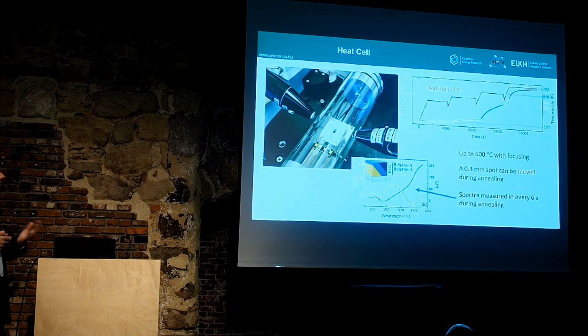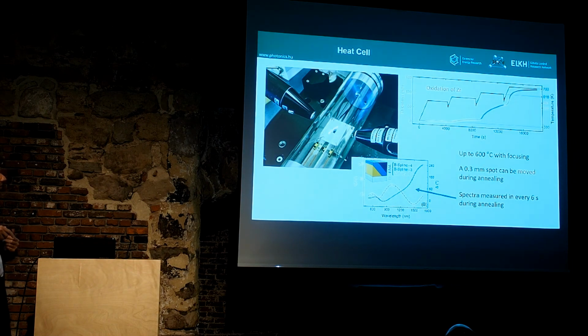The second example is also a non-destructive in-situ measurement. This is a heat stage. This is a ceramic plate. You can heat it up to 600 degrees C and put the sample on top, and you can focus the light inside this glass tube. The spot size is below 1 mm, and you can even move the spot along the axis of this tube. And this also has 1 second time resolution. You can see here part of the spectrum. It's even larger, from 190 nanometer to 1700. So it is 1400 measured data points in each second, basically.